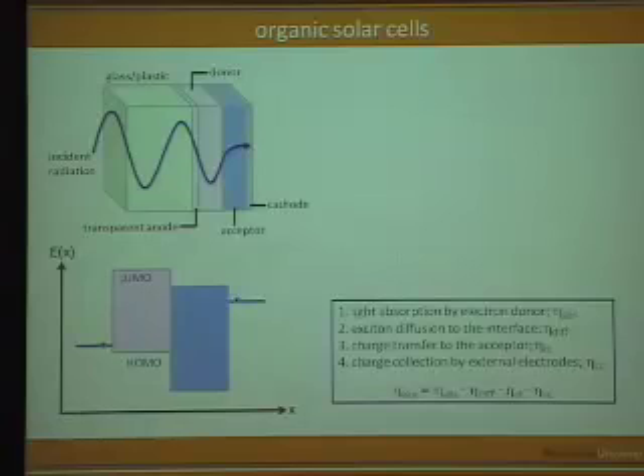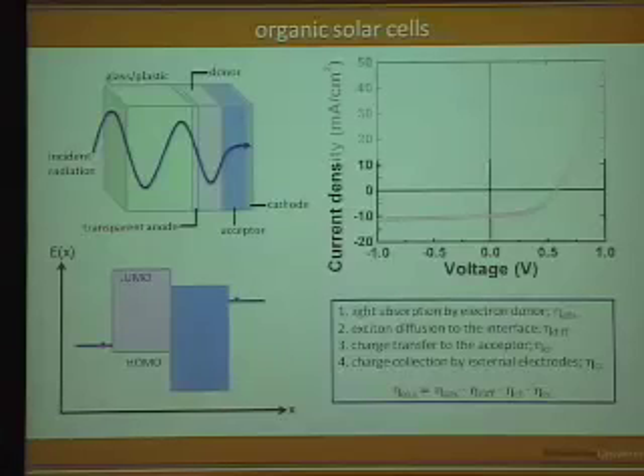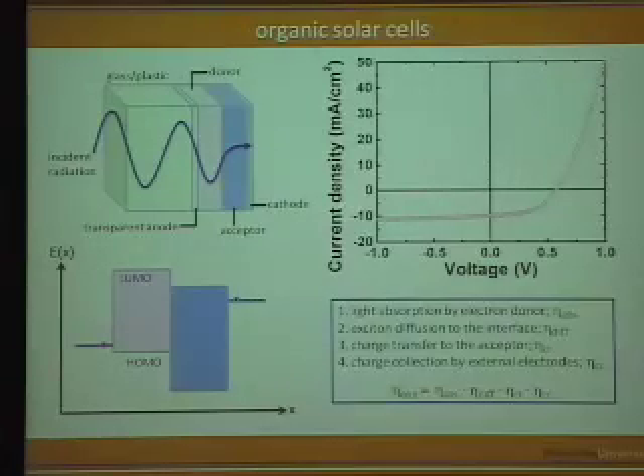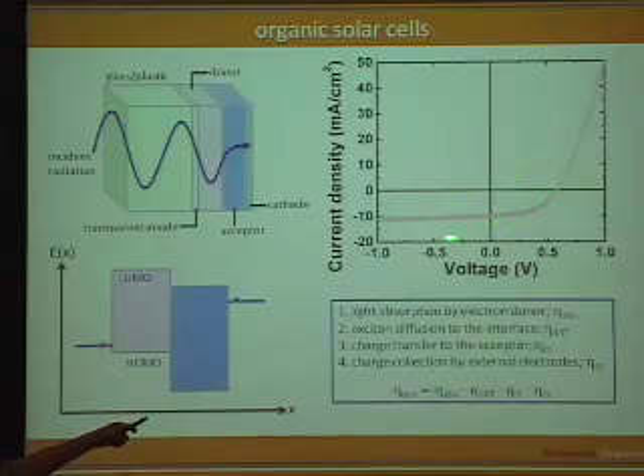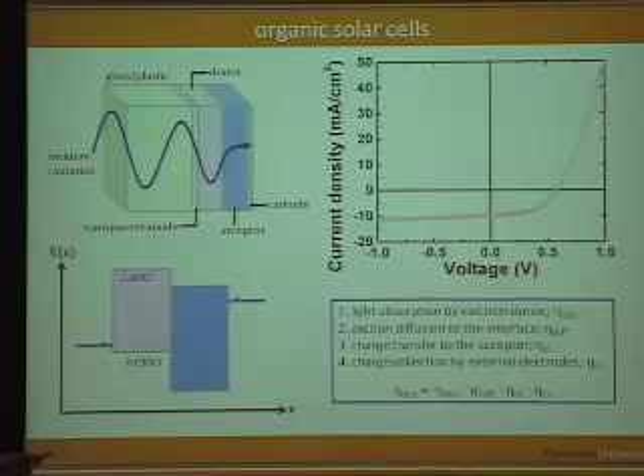Okay? And you can begin to understand why that is the case. The efficiency that's associated with a device is a compound of all these different efficiencies. So if you have one single step that's not efficient, that sort of propagates onwards. To characterize these devices, you plot the current density as a function of voltage, and you get a diode curve, and it's really the area here that's below the zero line that gives you how efficient your device is. The bigger the area, the better your devices are.